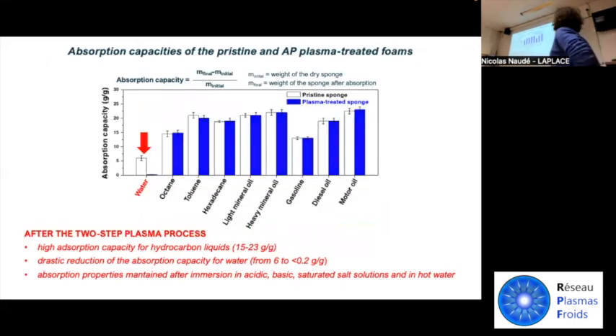So here, the absorption capacities of the pristine and plasma treated foams are reported for both water and various hydrocarbon solvents, hydrocarbon mixtures, also gasoline, diesel oil, motor oil. And as you can appreciate, the foam exhibits a high absorption capacity for hydrocarbon liquids before and after the plasma treatment. However, after the two-step plasma process, we observe a drastic reduction of the absorption capacity for water. And these absorption properties were maintained after immersion in acidic, basic, saturated salt solution of water, and so on.